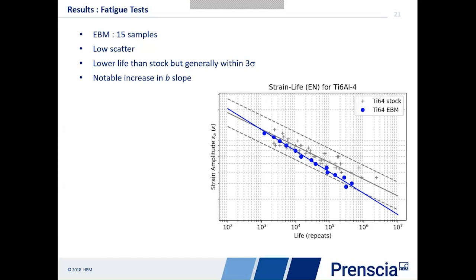So what we find is that at the low cycle fatigue end, they're tending to be similar material to the standard stock, in the same way as the tensile properties are similar. But at the high cycle fatigue end, we're seeing that the fatigue performance is not as good. And that's exactly what we would expect from these, because at the high cycle end, surface imperfections, porosity, irregularities become far more dominant. At the low cycle end, the load is the most important thing. But at the high cycle fatigue, it's all of the little things like surface effects, like porosity, which become increasingly more important. And so this is exactly what I'd expect.